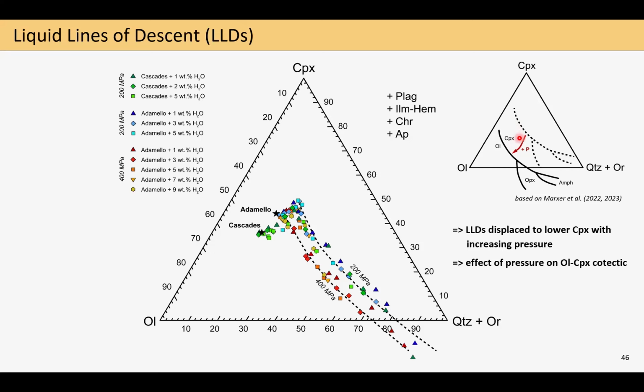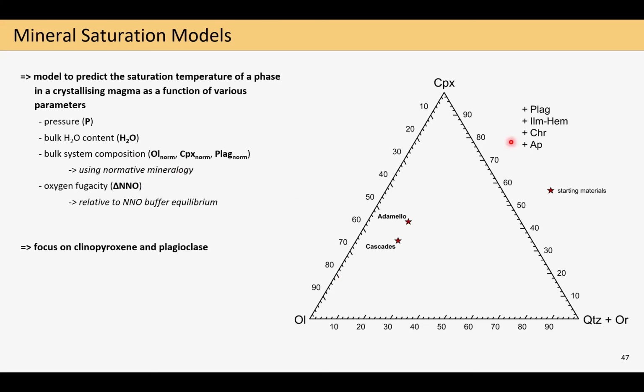So I can describe my experimental data, but as you might remember at the beginning of the second part, I told you that the idea here was also that we try now to quantify phase equilibria. And for this, the first idea I had was that I wanted to try to formulate some mineral saturation models, so an algorithm which allows you to predict the saturation temperature, so the highest temperature of crystallization of a mineral in a magma as a function of various parameters, where I'm currently trying to incorporate pressure, bulk water content, the bulk system composition, and the oxygen fugacity. Where for the bulk system composition, I had the idea to account for this using a normative mineralogy.